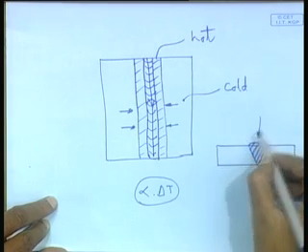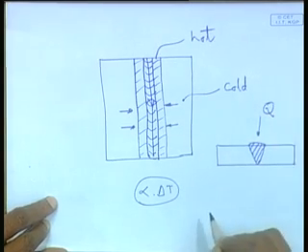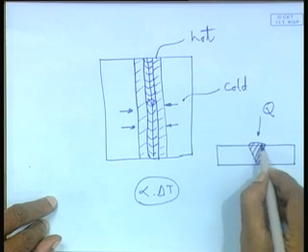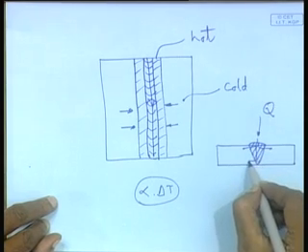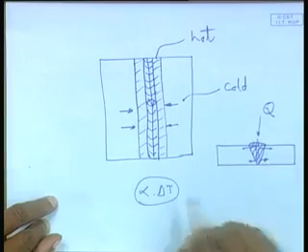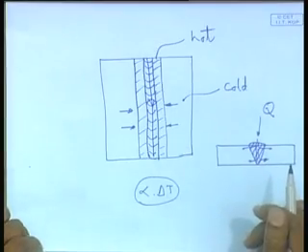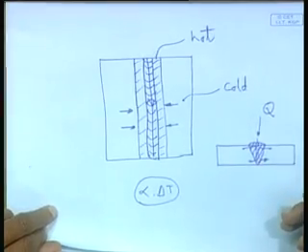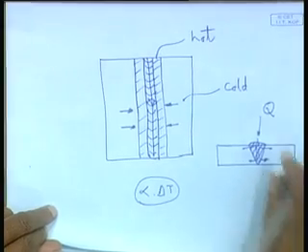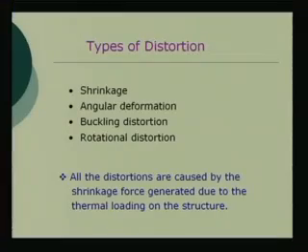If the welding is being done from the top, that means the heat source is coming from the top. You'll have more heat coming at the top, whereas less heat coming at the lower half of the plate, for the simple reason that heat conduction will be less, right? Thereby, again, it will lead to a different kind of deformations, right? So we see, because of this,